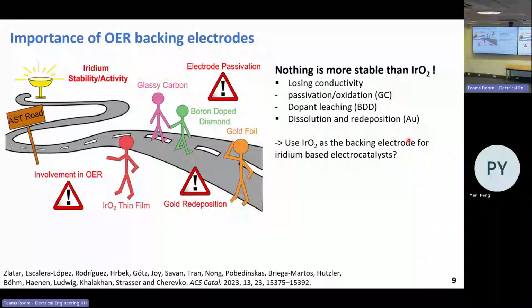However, recent publications showed gold is still problematic. In this paper, they compared different backing electrodes like glassy carbon, boron-doped diamond, gold, as well as iridium oxide itself. Each of them has their own problem. And the conclusion is that nothing is more stable than iridium oxide, and the degradation in performance is very likely from the backing electrode rather than the degradation of iridium oxide itself.